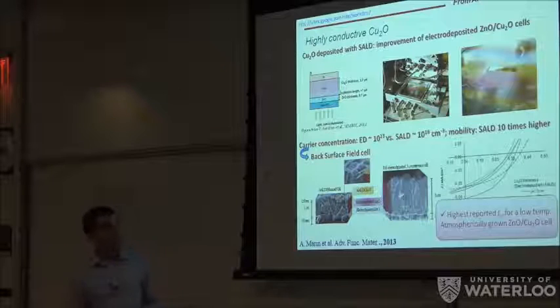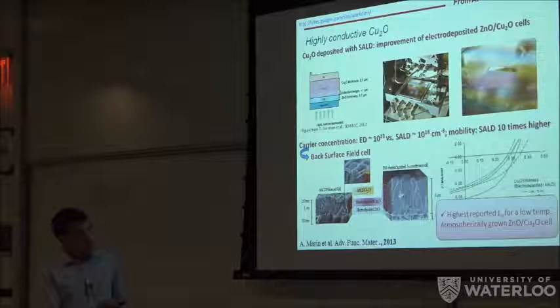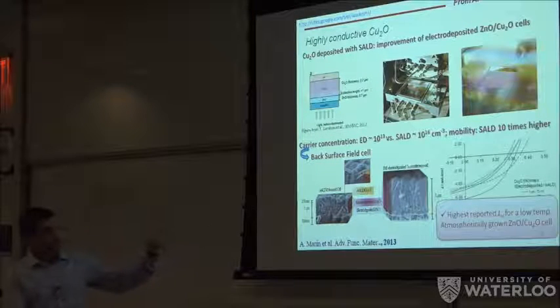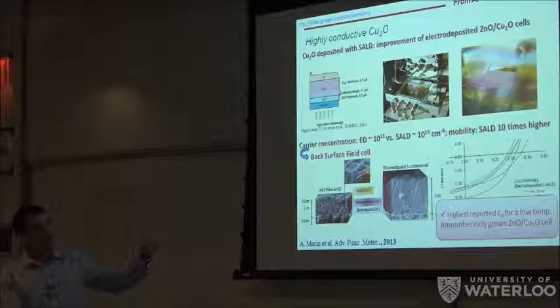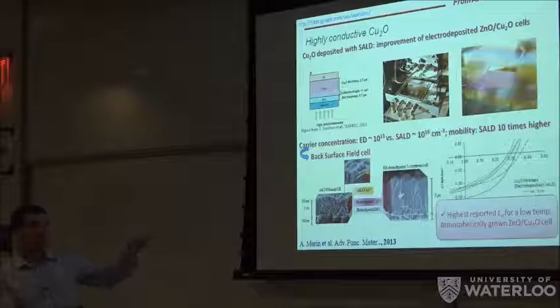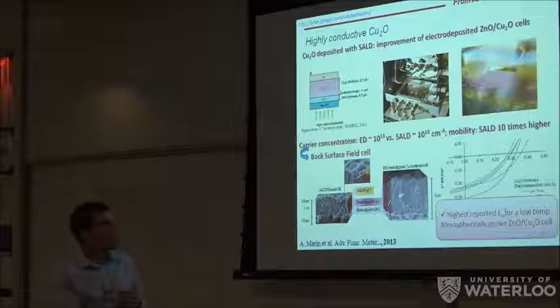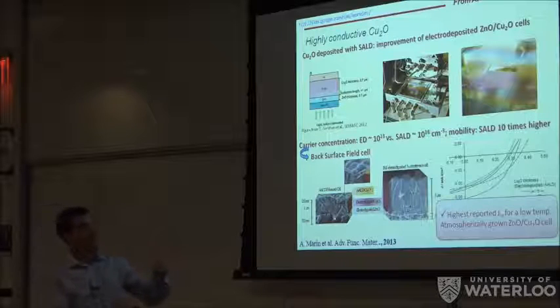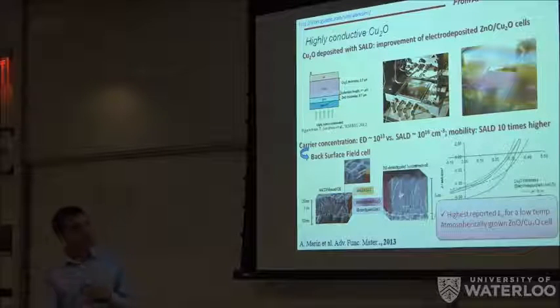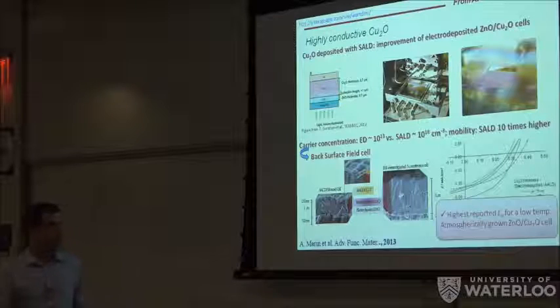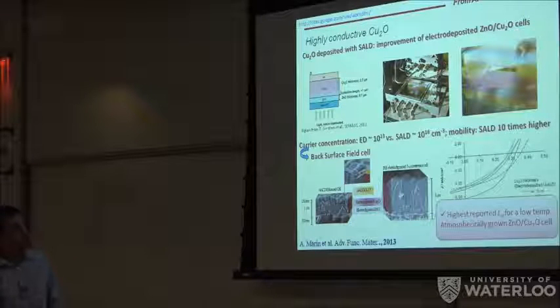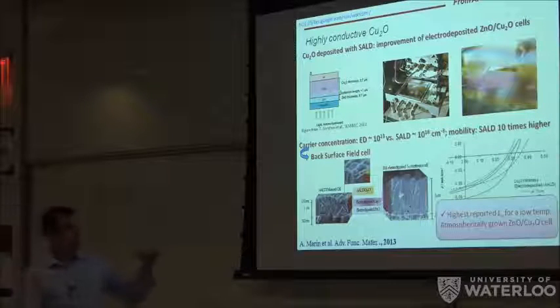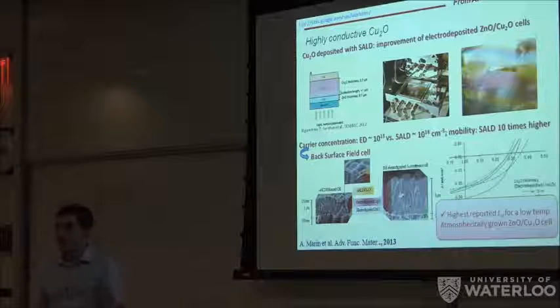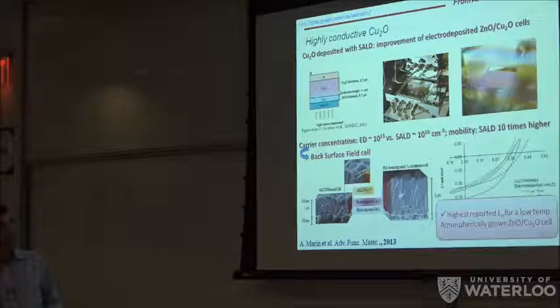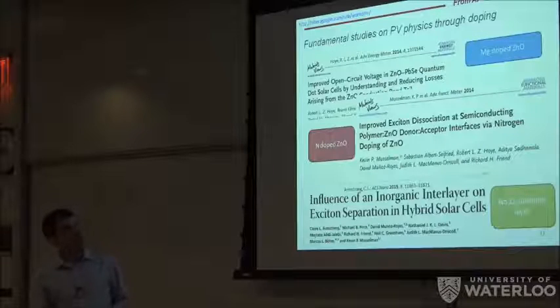and for chemical methods. You can see also that we managed to reduce the amount of cuprous oxide that you need to get this order of efficiency from 3 microns to 1 micron. So again, I won't go into the details of the physics of this device because it's quite complex and I don't have the time, but just a rapid example of how we could use our spatial atomic layer deposition system to improve the performance of our devices.